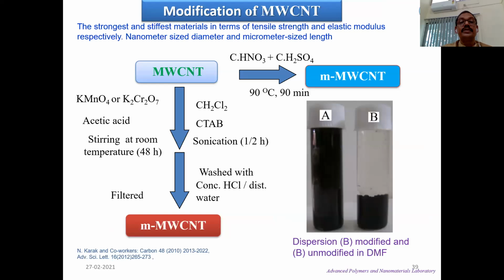We have also used multiwalled carbon nanotube, and as these have high aggregation among themselves because of strong van der Waals attraction and pi-pi bonds, they need to be functionalized. In most cases, oxidative functionalization is used. We have also initially used this, but as a result, their aspect ratio is reduced because you have to use very strong oxidizing agent.